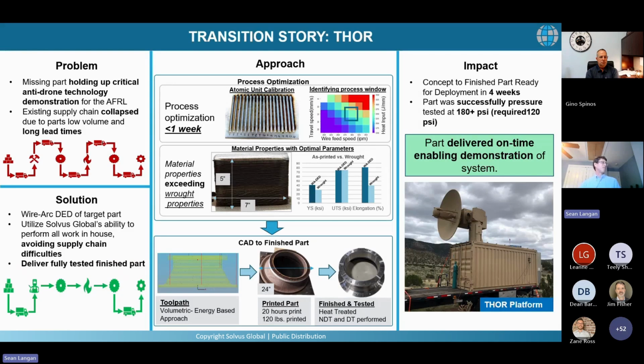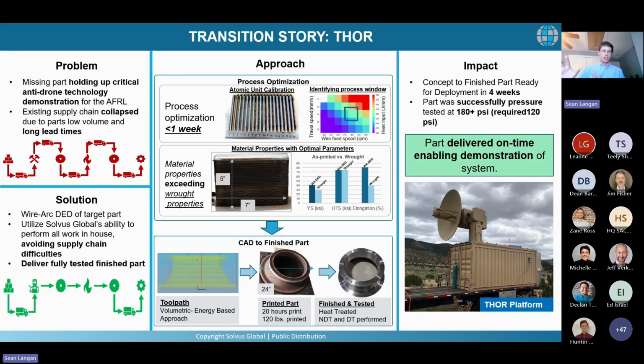Here I've got an example of this. There was a missing part that was holding up a really critical anti-drone technology demonstration for the AFRL. The existing supply chain wasn't letting them get the part when they needed it. They needed it within 6 weeks, and they were quoted 24 months, if I recall. So they came to us and said, "Can you help us out here?" And we said, "Absolutely." The problem was it was a material we'd never worked with before. But within 4 weeks, we were able to go from process optimization, that's laying down your first welds, to getting and tuning material properties to ensure they were what they needed to be, and go from the CAD to the finished part.